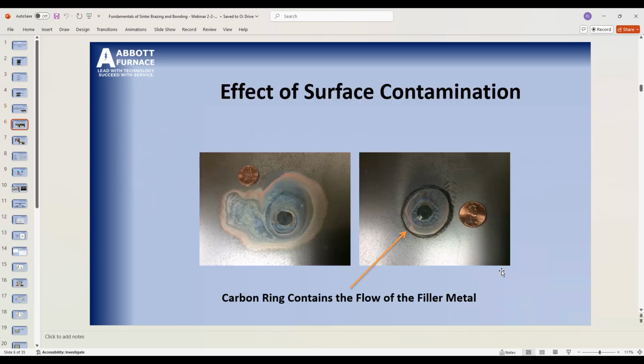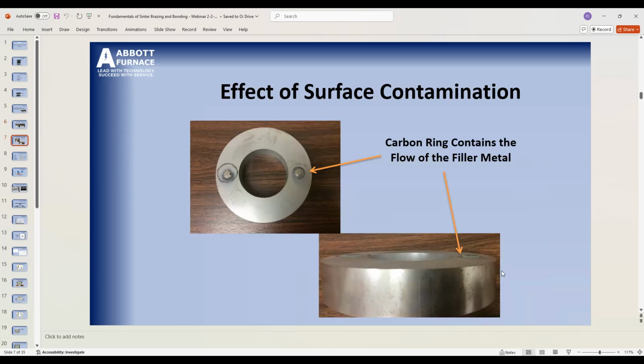And so here, this is blown up a little bit. You can see a little bit better how that carbon ring stops the flow of that filler metal. You can see it went right up to it on the right-hand side there, but it wouldn't go over it. And I also did this on a powdered metal part, okay? And so you can see here, I have a ring that's drawn kind of away from that pellet, and then one that's right up against it. And if you notice, the one that's right up against it, the filler metal actually humped up when it melted. It wouldn't cross that carbon ring.